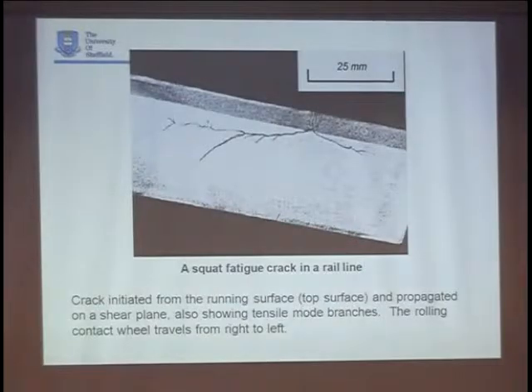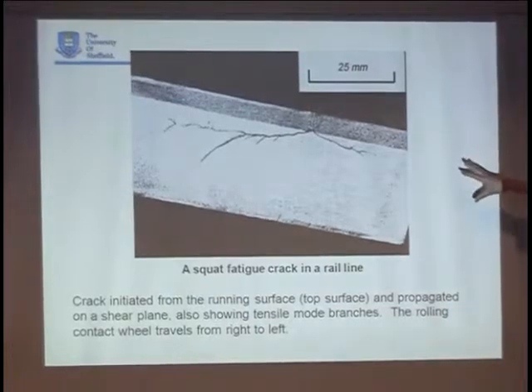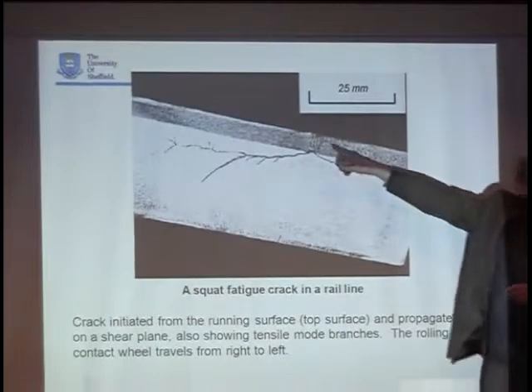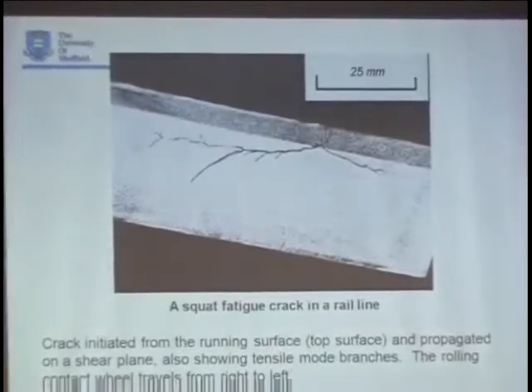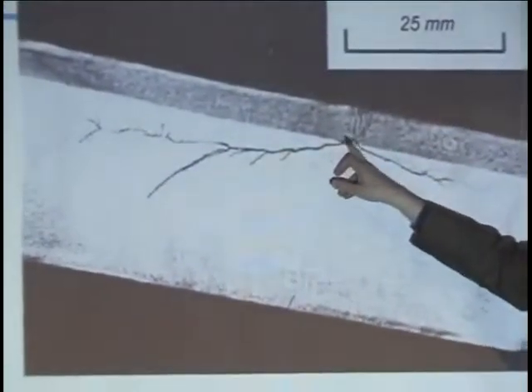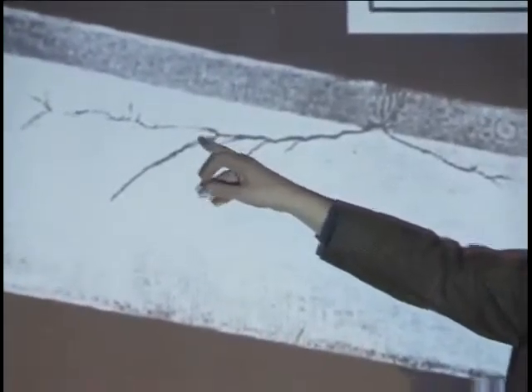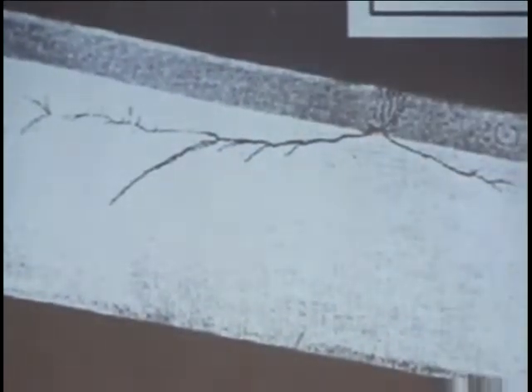Let's move on. Cracks do grow in Mode 2 in practice, of course. Even if you can't do it in the lab, they do in real life. This is an example that I use quite often. You may have seen it before. It's a railway line, and the top surface here is the rolling surface. We've got travelling rolling contact fatigue, and we get cracks in the railway line. And you see the cracks going along here at a fairly shallow angle to the surface.